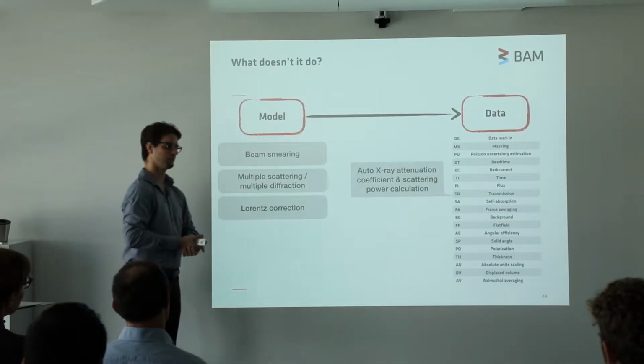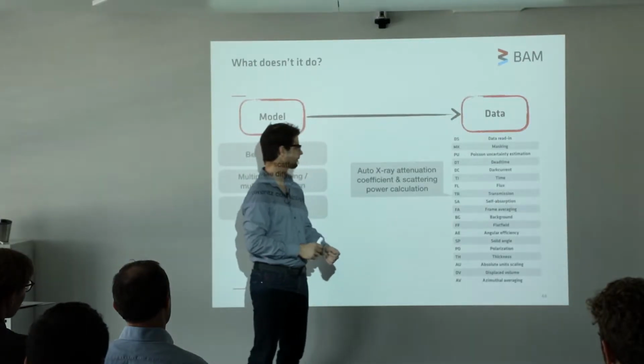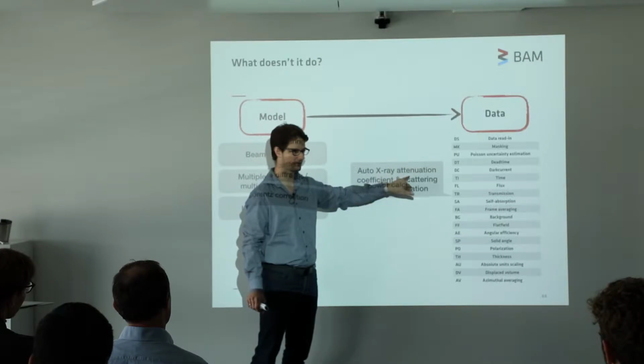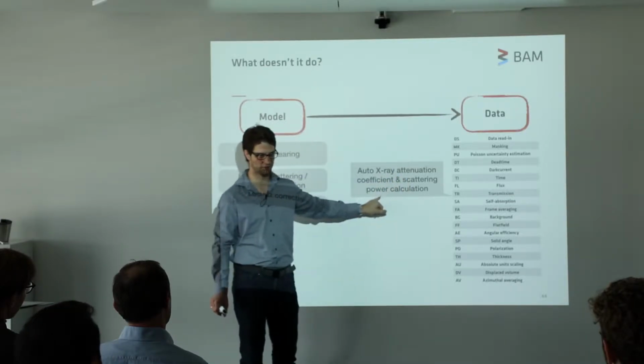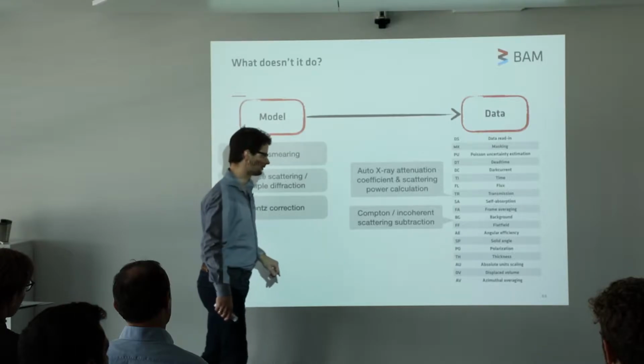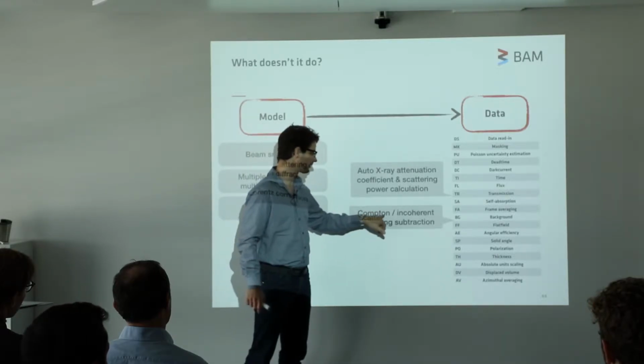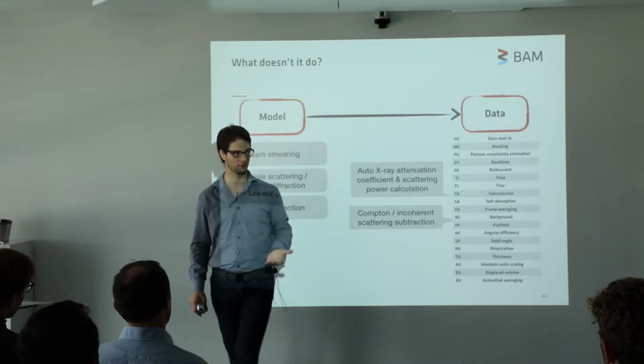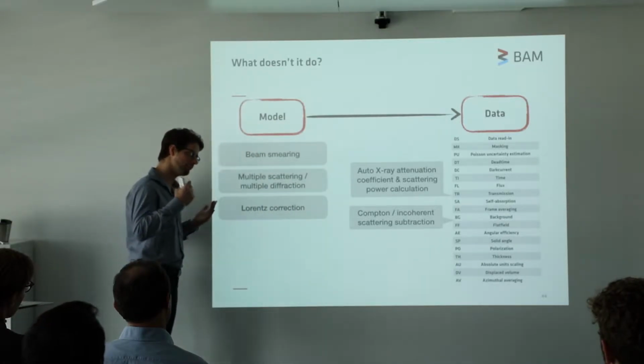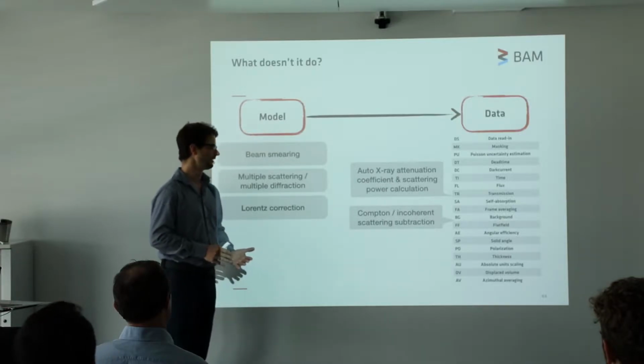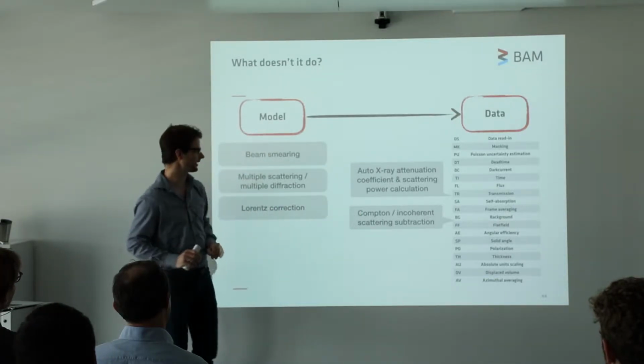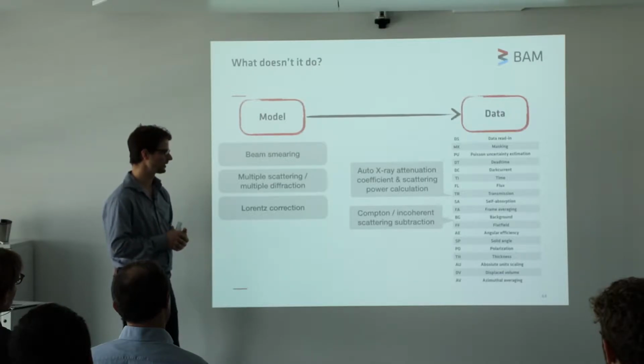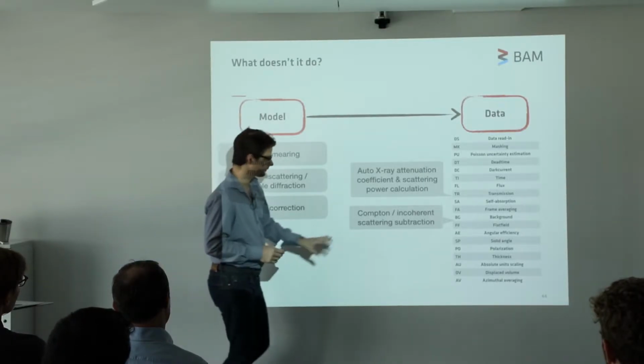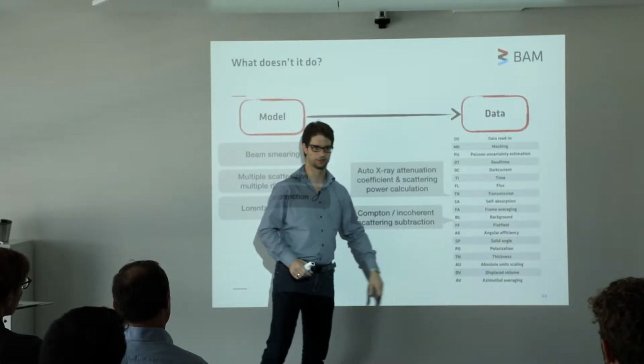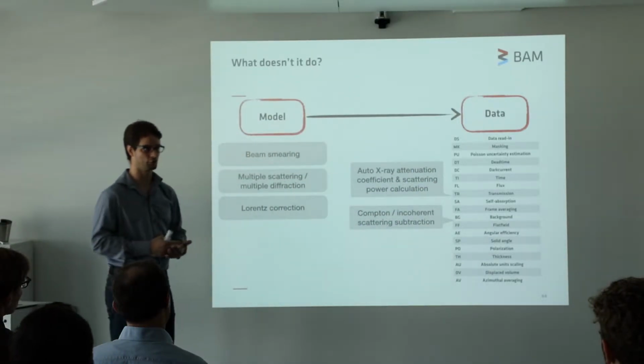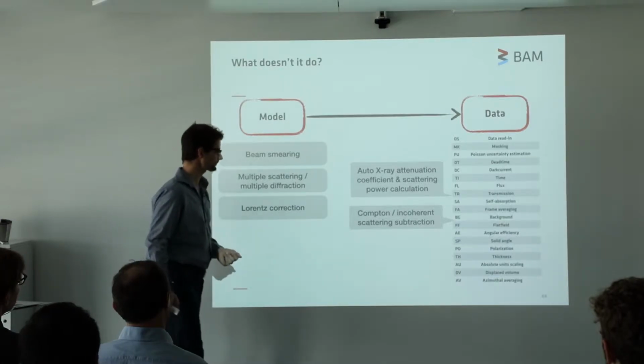So what doesn't it do yet? Well, we will calculate an automatic X-ray attenuation coefficient and a scattering power calculation, so that you've got your scattering power, that's nice, but also you can include the incoherent scattering. This isn't a big effect in X-ray scattering. In fact, most people just neglect it, and they're actually pretty correct in doing so. However, by including this, we may be able to get this data correction procedure applicable to neutron scattering and neutron diffraction as well, which would be kind of cool.